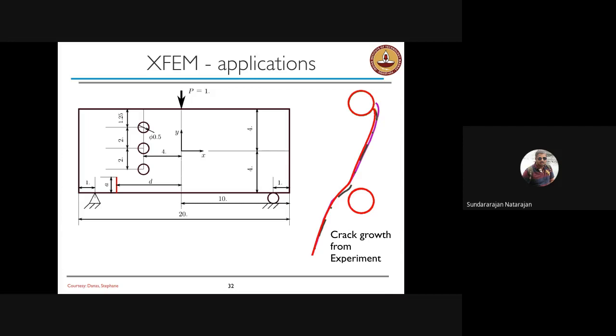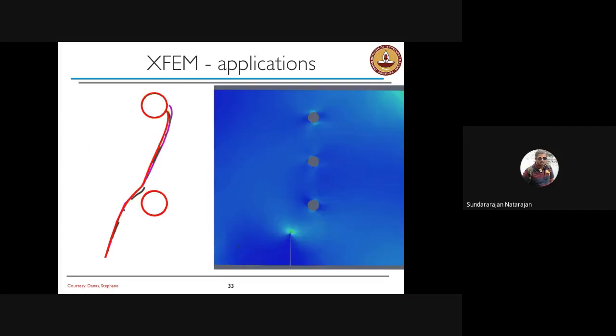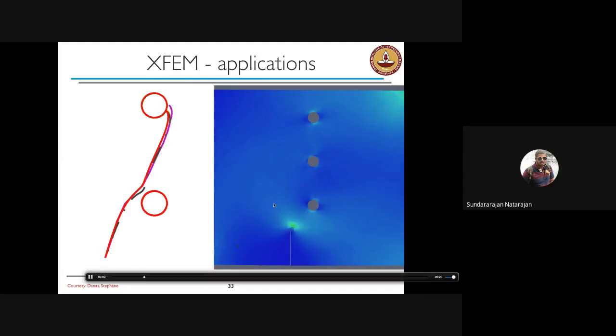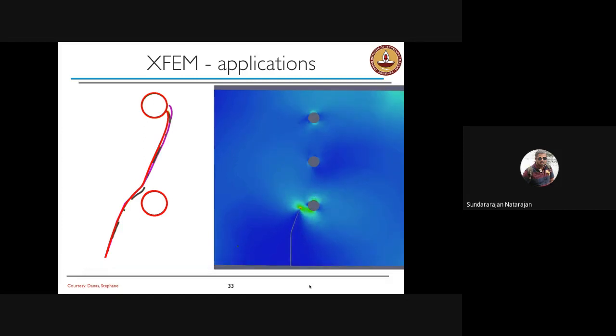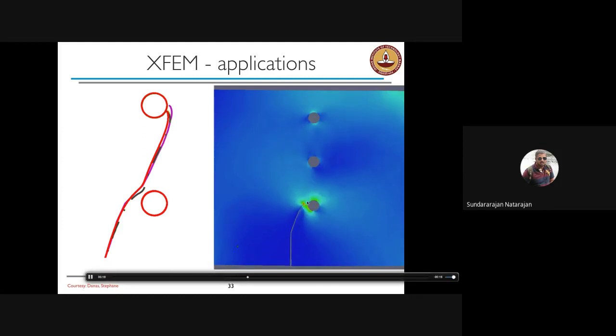And you also have to update the mesh every time the crack grows. What you see on the right, the red line and the purple line, are the crack growth from the experiments. And we try to solve this using XFEM. That's the animation that you would see. So this is a case where the distance is such that it bypasses the first hole and then goes and merges into the second hole.